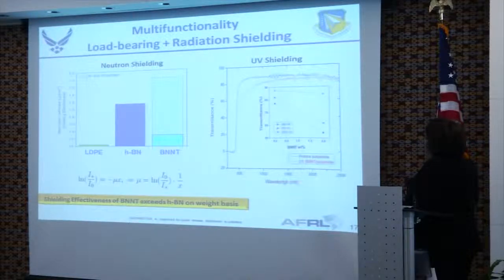Also, I won't harp on this, but I mentioned before the neutron shielding capability of the boron materials, and so here they've done some very initial work using a neutron source in residence at NASA, and looked at the shielding effectiveness, mu here, of different materials: low-density polyethylene, hexagonal boron nitride particles, and boron nitride nanotube particles. And because of differences in not having enough material volume, they didn't measure. This is 30% boron nitride particles, and this is only 5% boron nitride nanotube. And neither of these are at saturation.